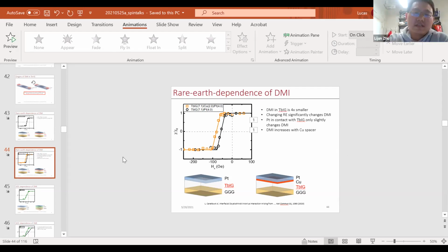So you say it's an interfacial DMI. Does that mean it's from the bottom interface with the substrate? Yeah, that's exactly it. Okay. So perhaps the choice of substrate matters. If you picked a different garnet substrate, you can dope these substrates. You can buy commercially doped substrates. That will very likely change the DMI as well, depending on how you dope it.